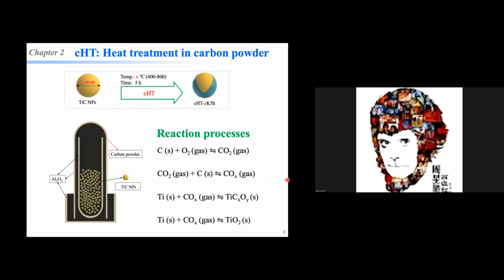The carbon can react with the oxygen from the air, and thus form CO2. CO2 can diffuse out and diffuse into the inside, and it can react continuously. We form COx maybe. COx can react with the Ti or TiC, and then they can form titanium dioxide or some kind of carbon-doped titanium dioxide, something like this. And we designed a series of experiments.